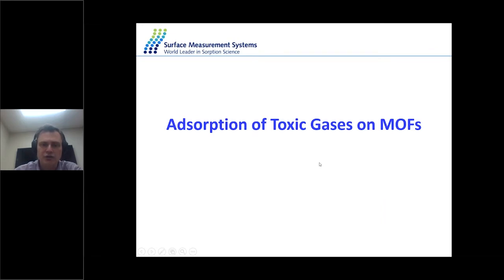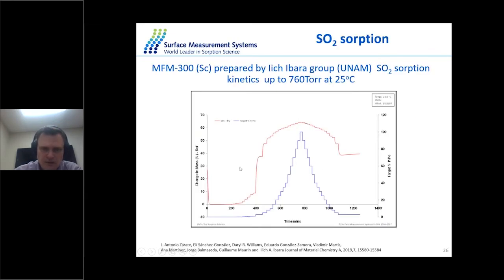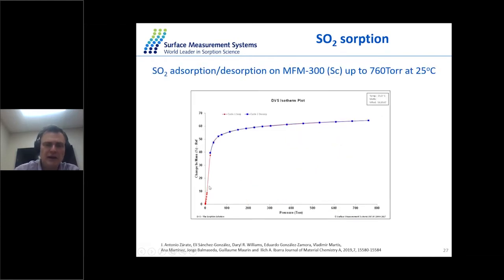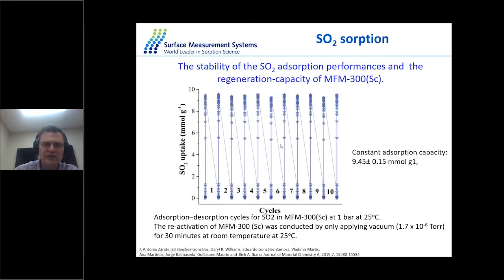Now we move to the adsorption of toxic gases on MOFs. Here we look at, let's say, an Sc MOF prepared by Ilich Ibarra from UNAM in Mexico. And look at the adsorption isotherm up to 1 bar for SO2. So in this case, you look at a pure SO2 gas. Again, we get nice type isotherms for pure SO2 gas, no hysteresis. Again, we look at the cycling. In this case, this material was cycled between 0 and 1 bar.